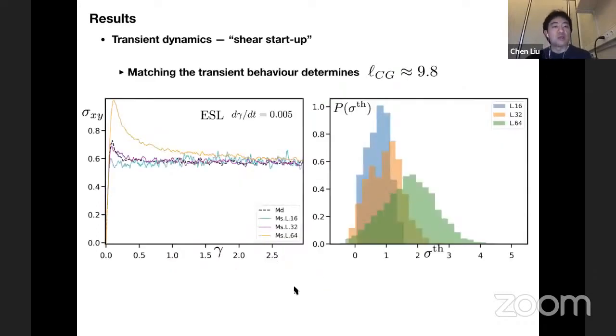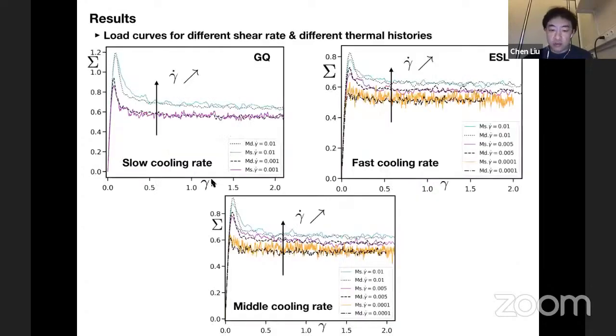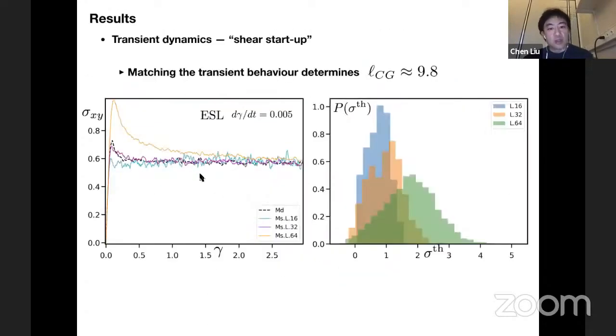And then I turn to the results of transient dynamics. First, I will talk about the shear startup experiment. By matching the meso data to the MD data, we can actually fix the correct coarse-graining length scale. In this figure on the left, the dashed lines are the MD data during the shear startup, and the different colors of solid lines correspond to the meso model with different mesh sizes. As you can see, only the purple one matches relatively well to the MD data.